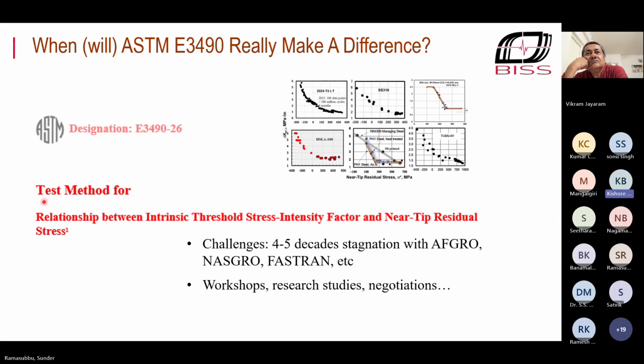For example, Miner's cumulative linear damage accumulation equation. Of course, Miner also developed a non-linear equation. Of course, damage is non-linear, but nobody talks about non-linear because that gets into more effort. But the result as such doesn't make much improvement because the fatigue life itself has a lot of scatter. So what I can foresee is that in NASGRO or AFGRO, whatever commercial software is available for crack growth prediction, one can ask to come out with your findings for improving your ΔK threshold value.